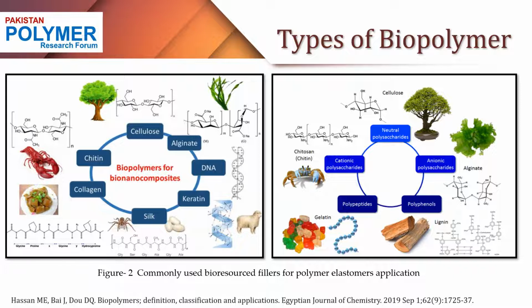As you can see in the structure of cellulose, chitin, and lignin, they all have OH bonds in the chemical structure that make them prone towards water. Because of this, they can easily absorb water and could reduce the mechanical properties of the end-use product. For this reason, these biopolymers must be surface treated with certain chemicals or additives that could enhance their compatibilization with the elastomers to improve the mechanical properties.